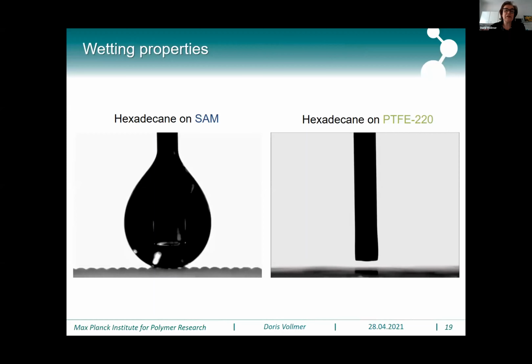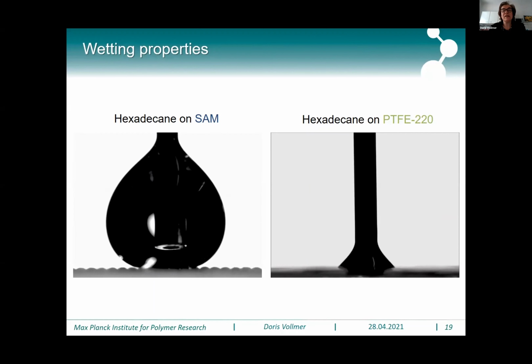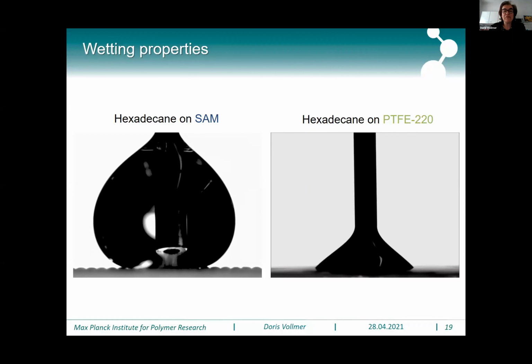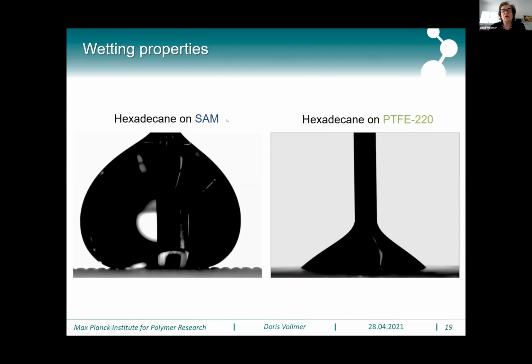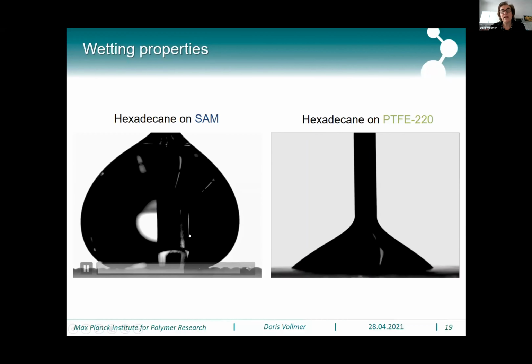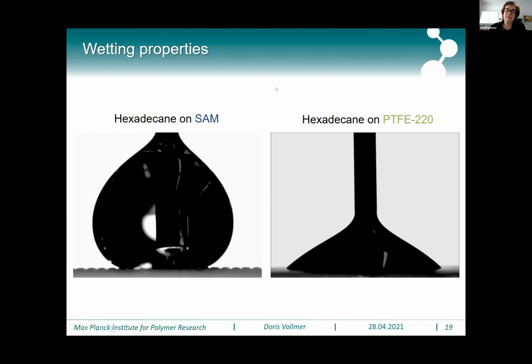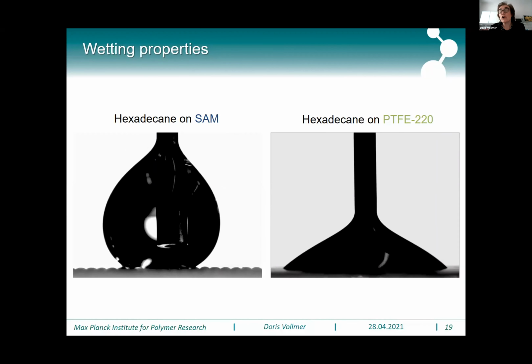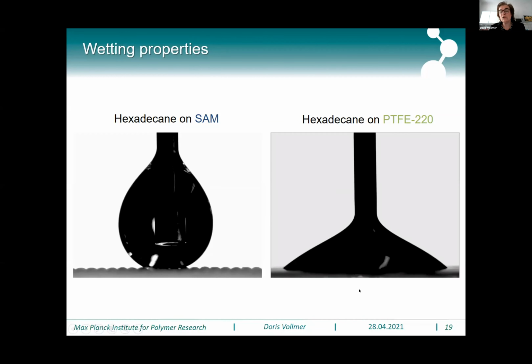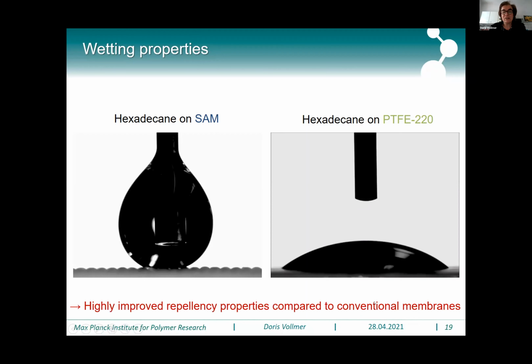Here you see, if we now place a droplet of hexadecane on our superamphiphobic surfaces, we have a huge contact angle. And the droplet does not stick, but it easily moves over the surface. Contrary to this, on the Teflon, hexadecane wets the surface. So we observed a strong increase of the repellency of the surfaces compared to conventional membranes.